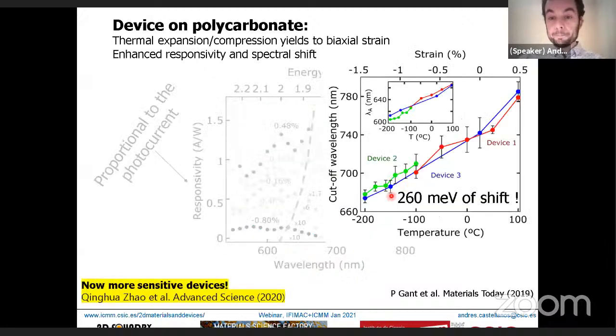What we have seen is that this cutoff wavelength shifts by a lot. We are talking here about around 260 milli-electron volts from minus 1.5% to plus 0.5%. So this is a lot. We are shifting the spectral sensitivity, the spectral window of our photodetector, by a lot just by changing the strain.